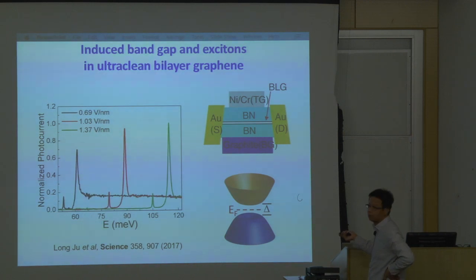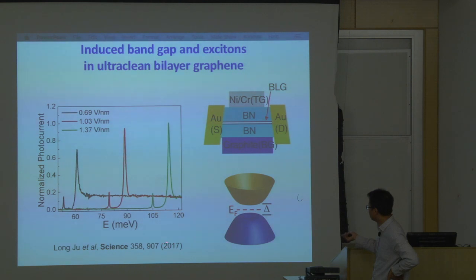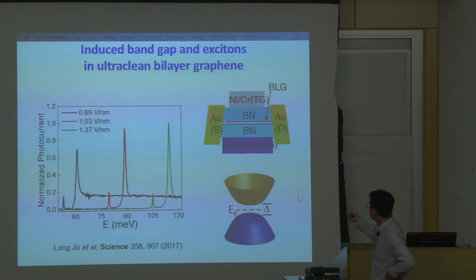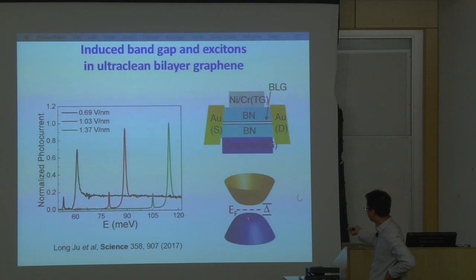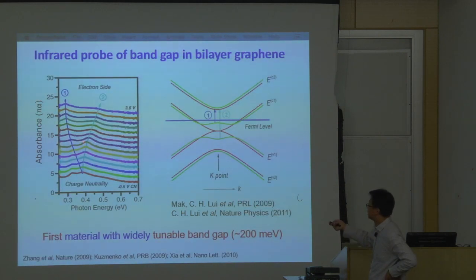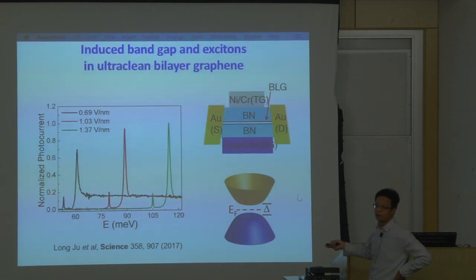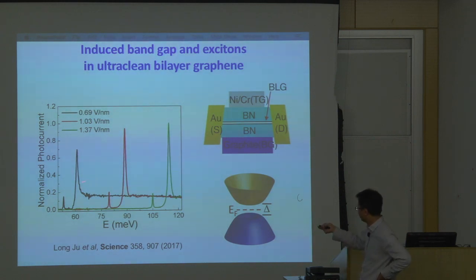This is the most recent result on band gap opening using the electric field effect, published a few months ago in Science. They use ultra-clean bilayer graphene encapsulated by boron nitride. By applying the electric field, they can open the gap and see the band gap transition — much sharper than our previous data. This shows the rapid development of 2D materials: they can even see the excitonic transition, very well tunable using the electric field effect.